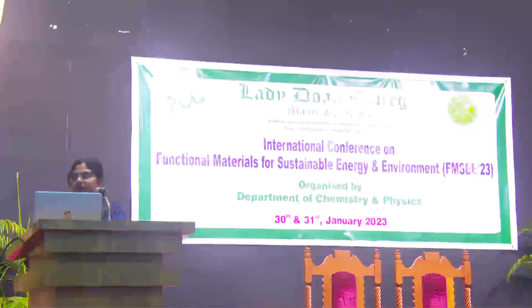In order to study more about the capacitive behavior and charge retention, we did electrochemical studies such as cyclic voltammetry, which was done in a 3-electrode system. From the calculations, we found that the specific capacitance was very high and very stable. Electrochemical impedance was also done, and the resistance was found to be very low.